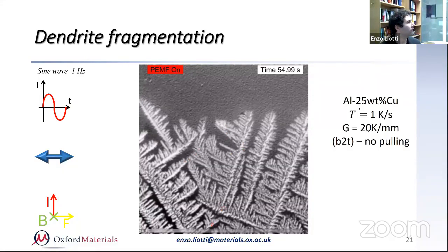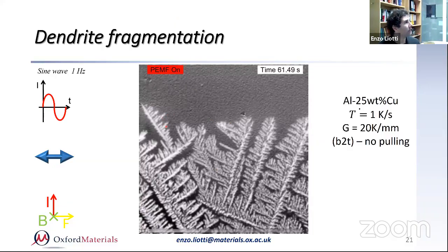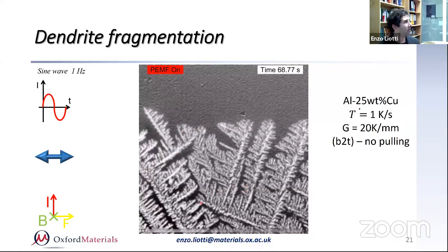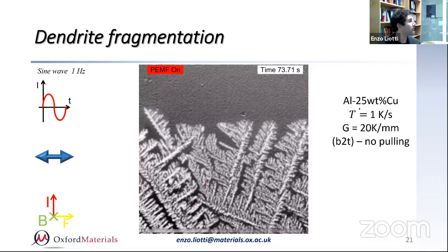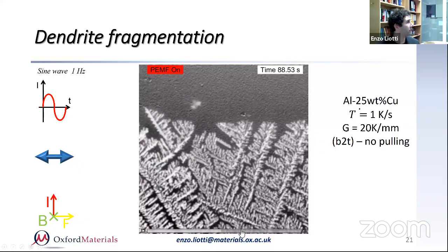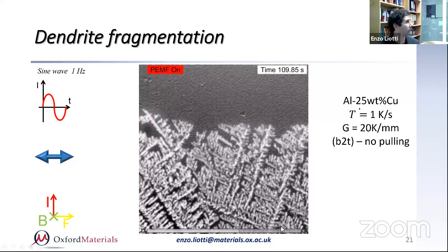So you can see, and if we speed up this process, I'll do it. You can see them moving with the flow. So it's a sinusoidal wave of 1 Hertz. So we are moving and steering the liquid on purpose. And you can see that it's taking primary, secondary, tertiary arms, breaking anything. And remember that in the mushy zone, you've got the liquid, and we are steering that liquid as well. So here I speed it up so it's a bit more frequent. You can see that it's very noticeable, and you've got a lot of this breaking.